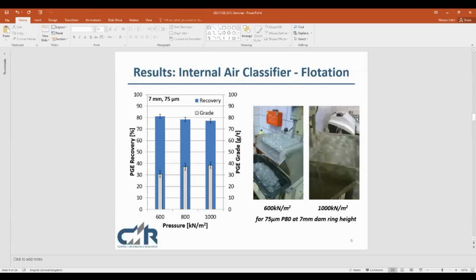So after a lot of querying this data, not really showing us what we expected, where we saw the differences is also in the solid water recovery, coming down to an issue of froth stability. So we have two pictures there on the right. This is for a 75 micron P80 at a dam ring height of 7 millimeters. And on the left, we're at a lower grinding pressure than on the right. So this is the first concentrate collected. So very, very high loading here for PGEs. And I'm sure you can all see a very visible difference there in the bubble structure.